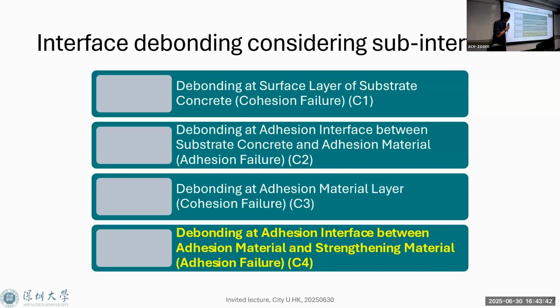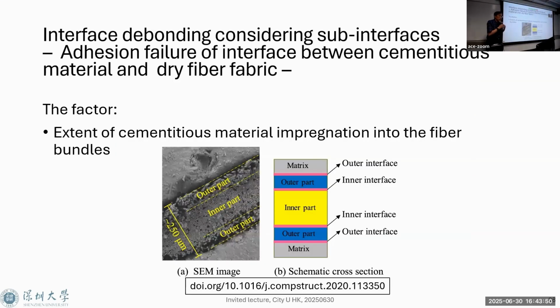The last one is debonding at the interface between the adhesion material and the strengthening material. So this time, debonding takes place between the strengthening material and the adhesion material. In this case, I only found one case. In this particular case, the extent of cementitious material impregnation into the fiber bundles is one of the key parameters. With more impregnation, the bonding strength becomes higher. So you have to be very careful where your debonding takes place. The controlling parameter is quite different in each case. Your conclusion may be completely wrong. So you have to be very careful.